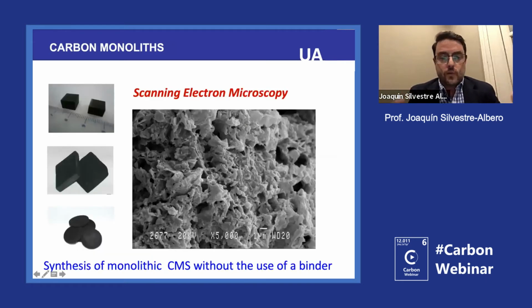So when we were removing the KOH from the system, and this is a scanning electron microscopy image of a lateral section of the monolith, we were able to see micron-sized cavities. So we are removing the chemical that we used for the activation, and of course we leave behind these big cavities, which are very convenient because those will be the motorways for the gas molecules to reach the inner porosity. And then the main question was, how is the inner porosity? How are the micro and meso cavities in this type of KOH activated carbon?